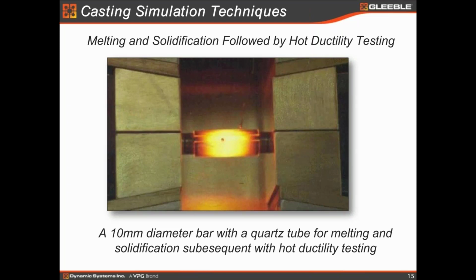So for most of the steels, you can simply just melt it to simulate the steel in the mold, and then you can just control solidification to simulate the casting cooling rate to generate the kind of dendrite you will see, and then you simulate the unbending process and a further subsequent hot rolling process by doing the hot ductility test to measure the reduction of area.